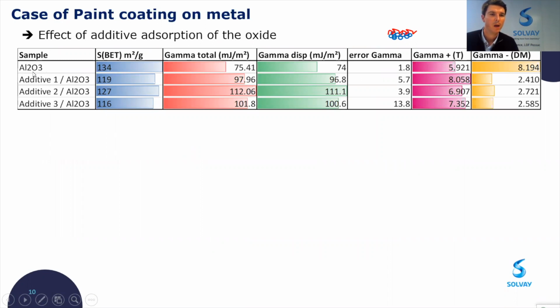As you can see, when we have some additive at the surface on the aluminum oxide, you tend to increase the surface energy of the materials and tend also to decrease the gamma minus, which is correlated with the basicity of your material. So you have interaction between the hydroxy groups of aluminum oxide with the additive, and it depends obviously on the type of additive adsorbed at the surface.